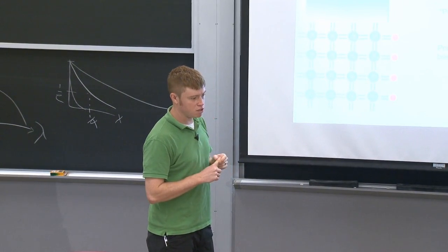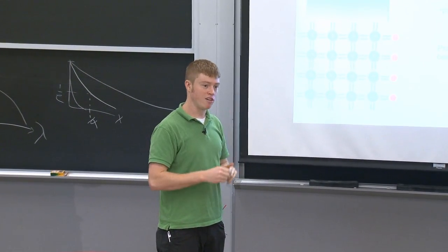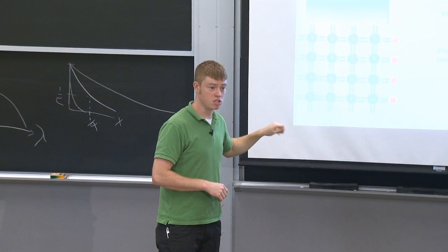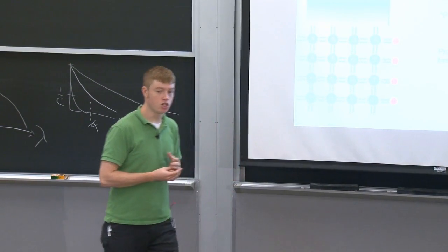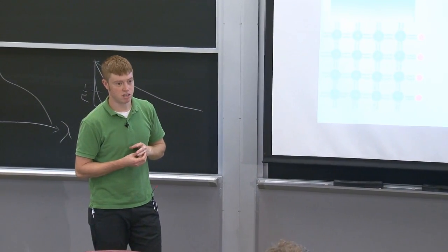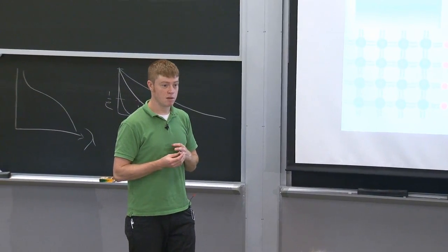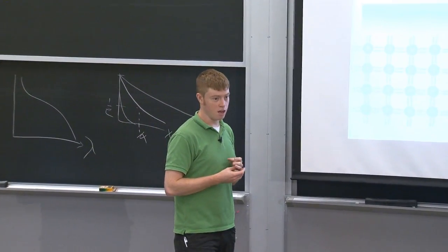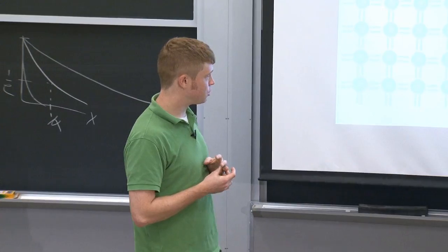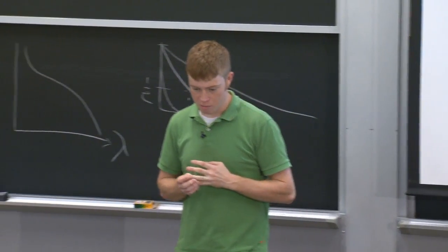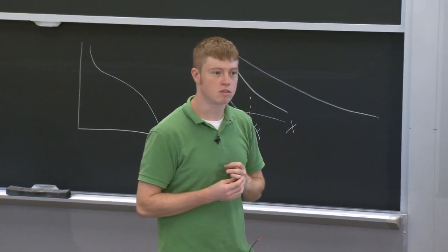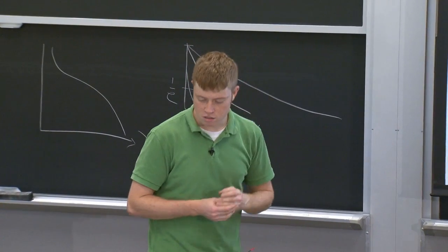Silicon oxide can be a good one. If you actually look at the structure, there's a few dangling bonds within there, but it can passivate most of them, just not all of them. Another good passivation technique is the silicon nitride ARC coating. It passivates the surface very well. So yeah, good question. And there are other ways to mitigate surface recombination as well, and we'll talk about that, I think, in either the next lecture or the one after that.